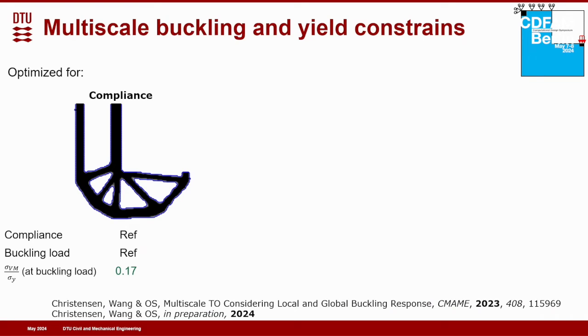So the first design here, this is again this L-beam structure. It's designed with a topology optimization approach where we allow microstructure. So we allow isotropic triangular microstructure, but as I said earlier, that is not needed. It's not good for doing stiffness design alone. So if you're just minimizing the compliance, we get this structure. This is the reference structure. I'm listing the compliance, the buckling load, and then also the yield load for these structures.